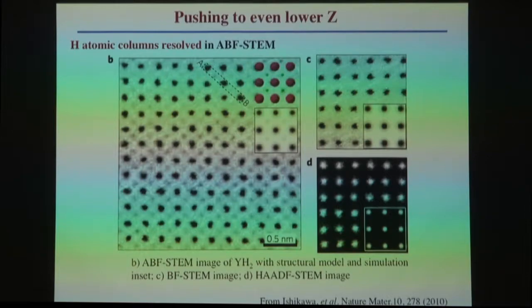This is yttrium hydride. Here is a simulation saying, okay, very faint, but now in the experimental image, you are able to see contrast, albeit not very strong. You don't expect it. Hydrogen's quite low in Z, as it were. Can't go any lower. But we are able to see, in this case, hydrogen atom columns in annular bright field in this sample of yttrium hydride. And so that might be of interest to some of you here trying to do annular bright field to see the hydrogen atoms in some of your hydrogen storage materials.